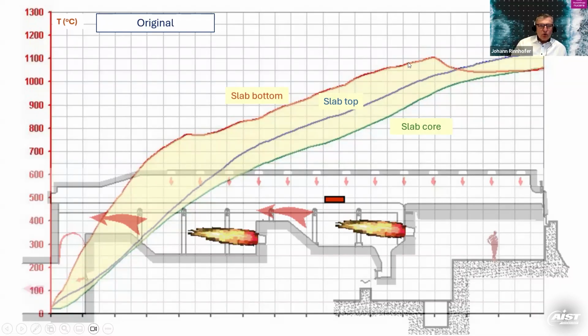That means we have to put all the energy which is needed into the slab in that area on the left side. So there was no option to heat in that area. So equalizing is shown here now. So we lose temperature again, and in the end, we have a certain temperature difference between bottom and top at the end of the heating process here, and we go into the rolling mill. So that is not ideal in terms of scaling. This is not ideal in terms of energy consumption, and so on and so on.